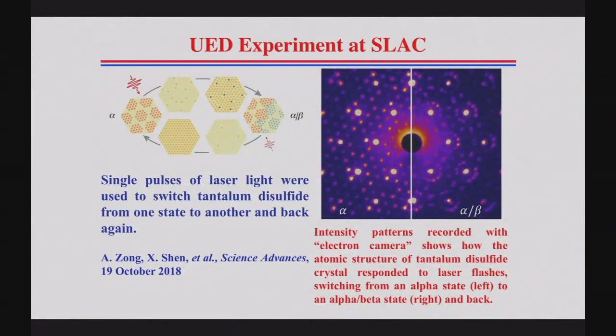In tantalum disulfide, you have electrons, and these electrons arrange themselves in the form of a wave. This wave is charged, and it is called a charge density wave. There has been a lot of work done on how the charge density wave in this material changes with temperature. So you're measuring resistivity as a function of temperature, and there are different regimes. And the question was, can you probe these different regimes? Resistivity versus temperature is an easy measurement. Can you tell where the atoms are sitting and how they're transforming, using an experimental probe?